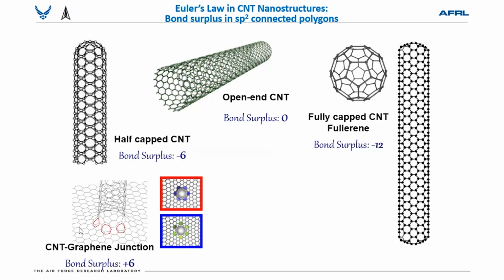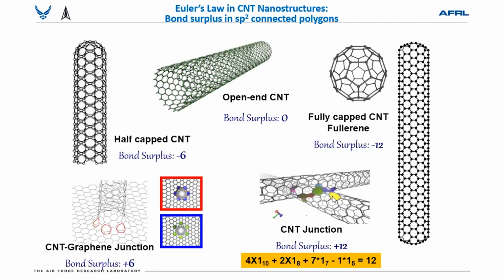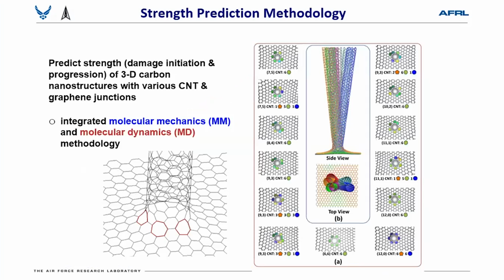For a junction like graphene to CNT, you need 7-member rings that bring bond surplus plus 6. For a CNT-CNT junction, such abnormality, meaning deviation from 6-member to 7 or 5, with minimum surface energy of the surface topology, brings bond surplus to plus 12. That's the basic design concept in terms of creating a junction from a strength point of view for carbon nanotube structure.